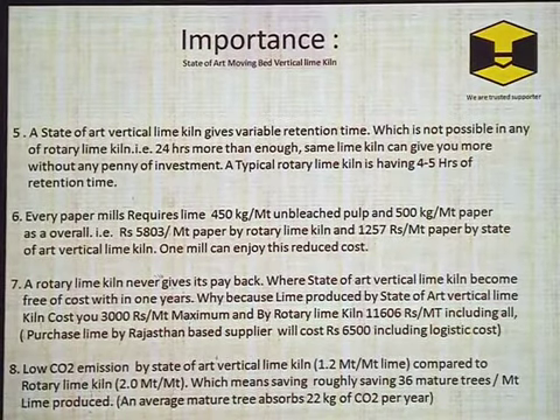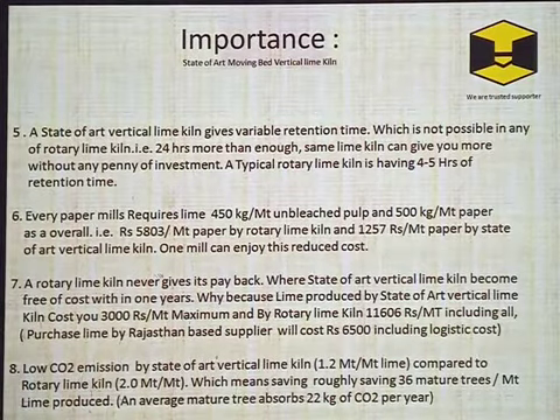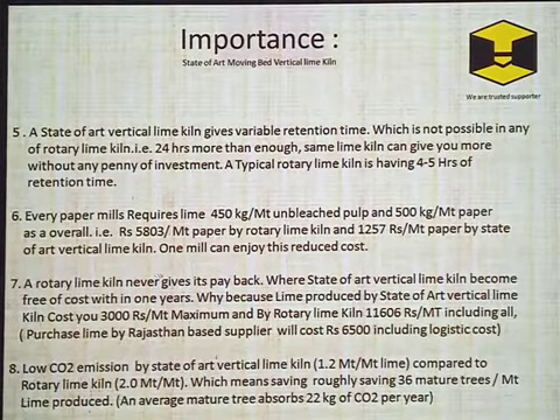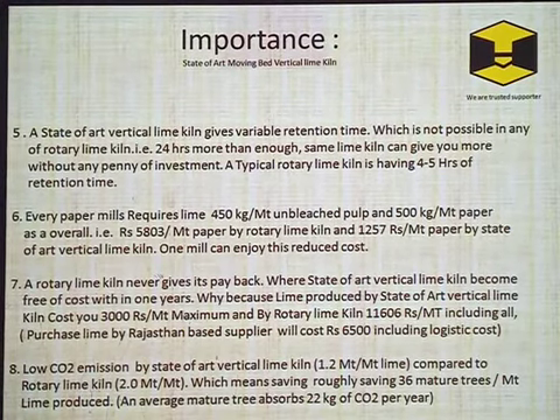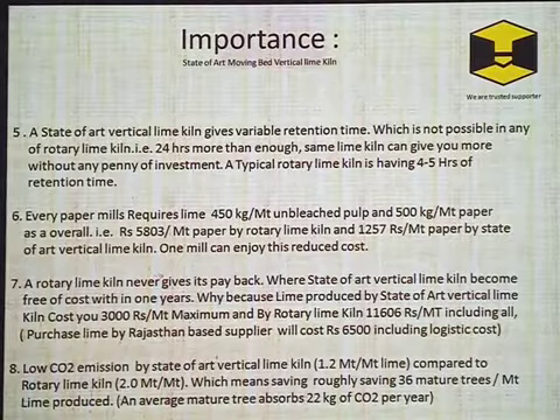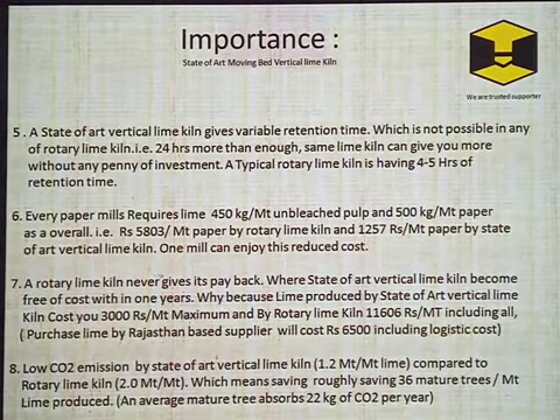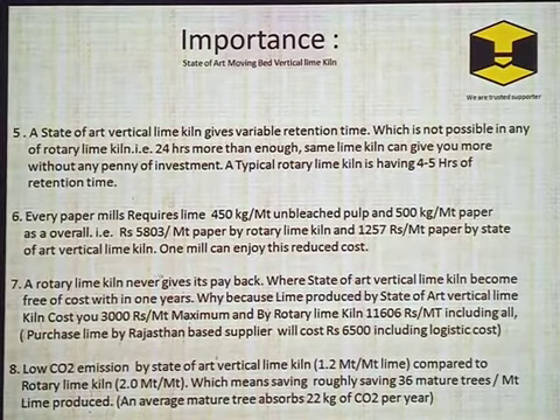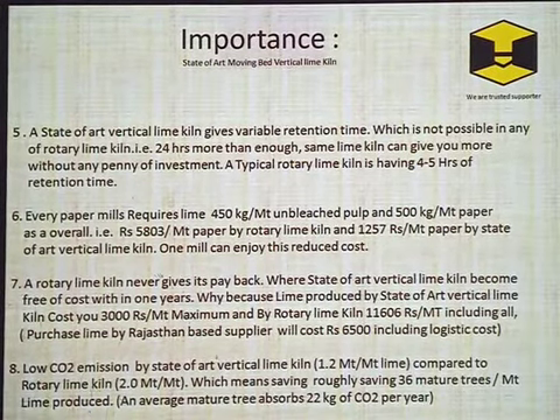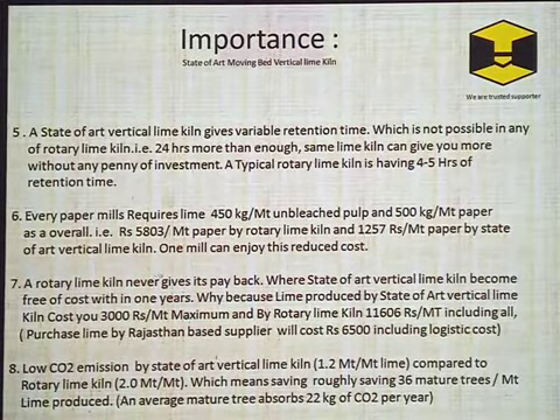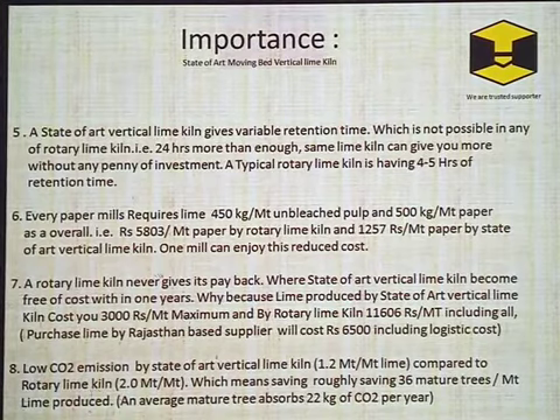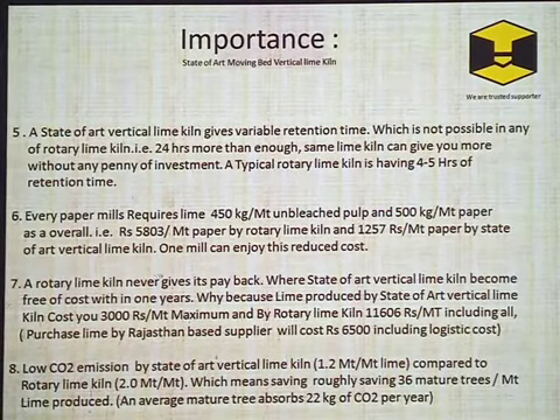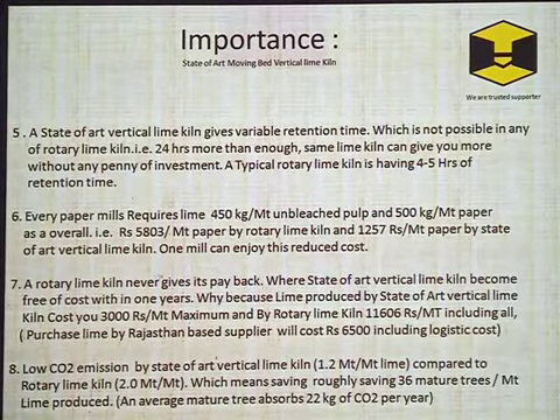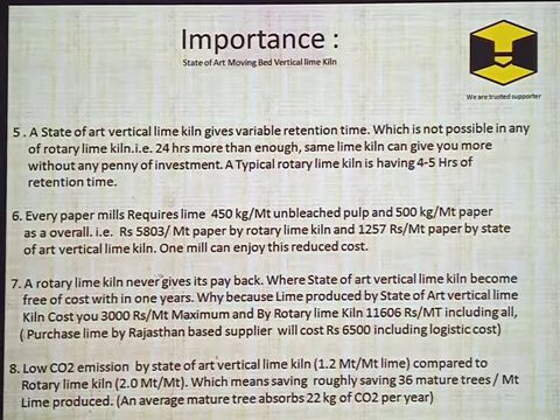Every paper mill requires 450 kg of lime to produce a metric ton of unbleached pulp, and 500 kg of lime to produce a metric ton of paper. So 5,803 rupees is the cost contribution due to lime alone in manufacturing paper by rotary lime kiln, and by state of art vertical lime kiln it is only 1,257. A rotary lime kiln never gives its payback, because the lime produced is very costly compared to the other two technologies. Emission is very low in the state of art vertical lime kiln.